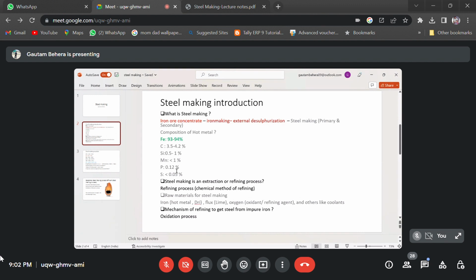And also we are adding some manganese ore in the blast furnace. You remember? We charge manganese ore. Why? One of the raw materials in blast furnace iron making is manganese ore. Because it reacts with sulfur to form manganese sulfide. Very good. Manganese ore will reduce to manganese, and manganese reacts with sulfur to form manganese sulfide. In this way, manganese sulfide will join the slag phase, and we can remove as much sulfur as possible in the form of manganese sulfide. Very good.